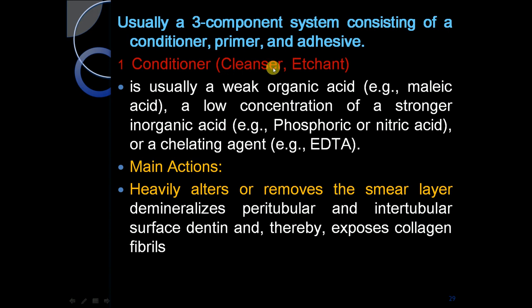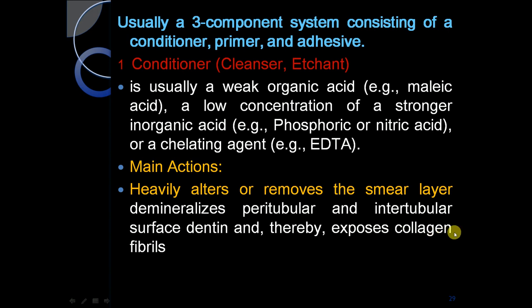The conditioner acts as a cleanser and conditioning agent. It is usually a weak organic acid such as maleic acid, a low concentration of stronger inorganic acid such as phosphoric or nitric acid, or a chelating agent such as EDTA. Its main action is to heavily alter or remove the smear layer, demineralize peritubular and intertubular dentine surface, and thereby expose collagen fibrils.